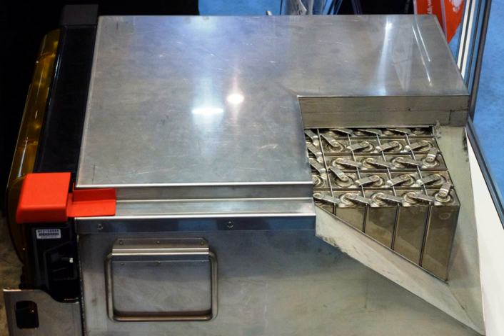The sodium-sulfur battery, along with the related lithium-sulfur battery, employs cheap and abundant electrode materials. It was the first alkali metal commercial battery, using liquid sulfur for the positive electrode and a ceramic tube of beta-alumina solid electrolyte. Insulator corrosion was a problem because they gradually became conductive and the self-discharge rate increased. Because of their high specific power, NAS batteries have been proposed for space applications and were successfully tested on space shuttle mission STS-87 in 1997, and have also been proposed for the high-temperature environment of Venus.